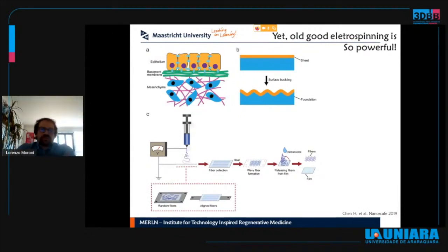Now, changing here from 3D printed scaffolds to electrospun scaffolds, one of the main limitations of such scaffolds is also that typically cells have a difficult time penetrating through a full three-dimensional construct, so that oftentimes electrospun scaffolds are considered semi-3D or still a sort of 2.5D system because of this lack of cell penetration inside thick electrospun meshes.